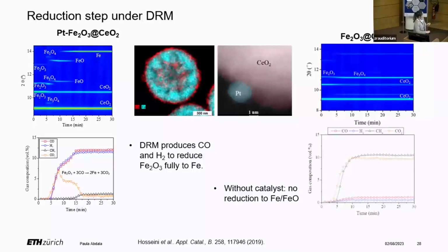This is the diffraction data. So here we have ceria, initially Fe2O3, which gets reduced all the way to iron via these two intermediates. And when we look at the gas phase, we see a high conversion of methane and CO2, but in between we produce CO2 by the reduction of iron. And yes, so this basically proves the concept of the dry reforming of methane at the particle level.